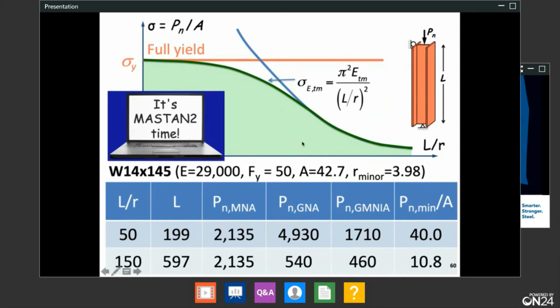And in this case, for an L over r of 50, we're somewhere around here, we're hitting the green curve at 40 ksi instead of the full 50. At an L over r of 150, we can only get to about one-fifth of the yield strength of the material. So, yeah, kind of interesting.